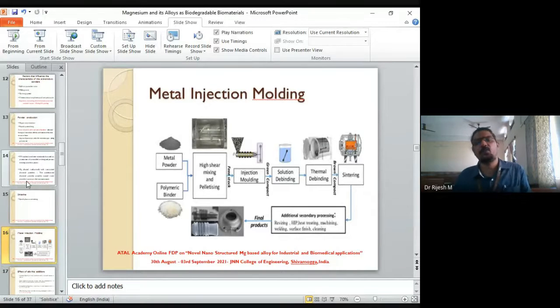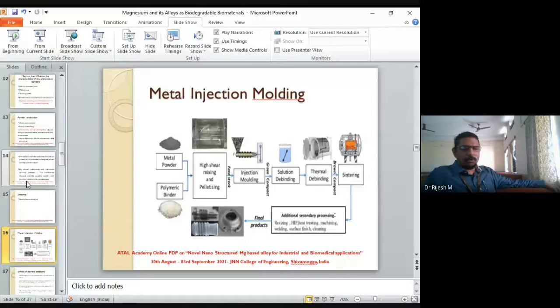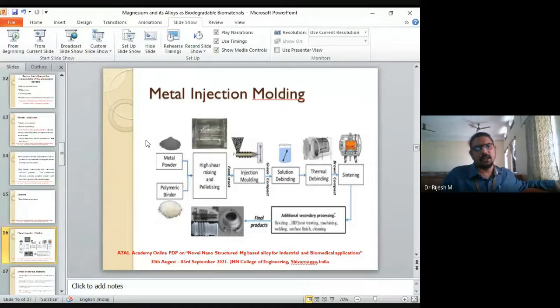Another way in which you make this is called metal injection molding. This is very common in the case of polymers, but in metals we do it by mixing in a binder. We take metal powders and polymer binders, do high shear mixing, and then pelletization. These pellets are fed into an injection molding machine where the particles are injected into the mold.